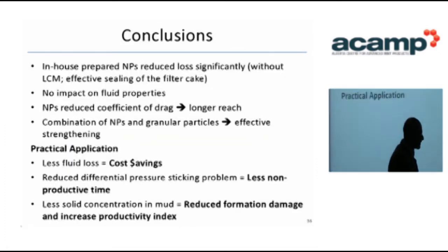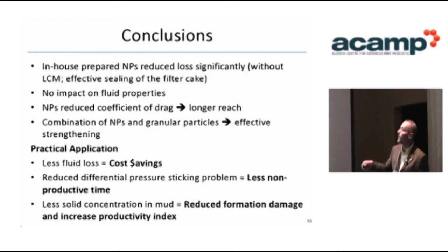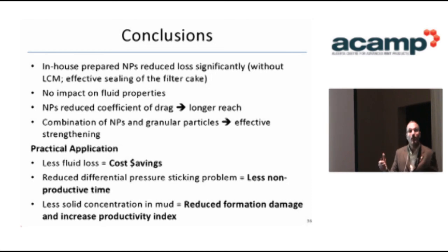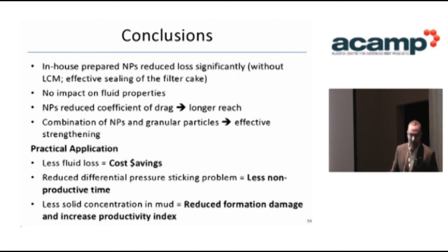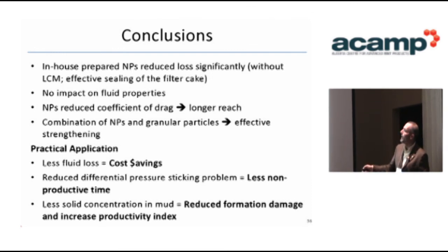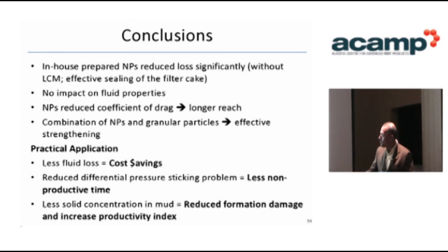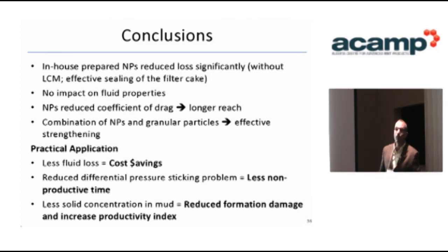In conclusions, the in-house prepared nanoparticles showed much better performance than commercial nanoparticles. They reduced fluid loss without LCMs and achieved effective sealing while the filter cake maintained its integrity. There was no negative impact on drilling fluid properties. The nanoparticles also reduced the drag coefficient, which is beneficial for longer-reach drilling — we could extend drilling at a given stroke. A combination of nanoparticles and granular particles also showed effective wellbore strengthening, and combining all these attributes together yields significant cost savings.